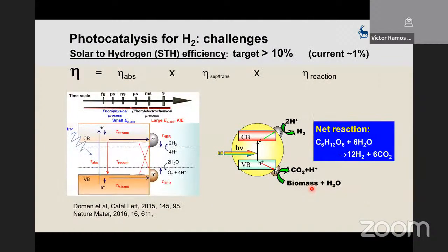So I mentioned the time scale. For those in the audience familiar with solid state physics, the time scale in a semiconductor photocatalysis process is really complex, from femtosecond to second. When the photon hits the surface, that happens in a femtosecond, and then the charge separation and transfer is nanosecond to microsecond, and of course the surface reaction is happening within seconds to minutes.